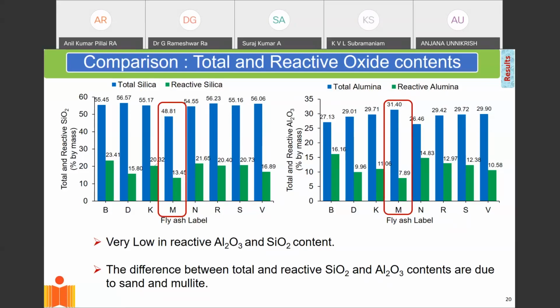can replace in cement. And we've developed now algorithms and procedures which allow us to optimize exactly the amount of fly ash that we can replace in cement, so that we don't compromise the properties that come out of this blended cement, where we are using cement and fly ash together, by looking at the reactive silica that is present. The other thing I want to point out is the reactive alumina.